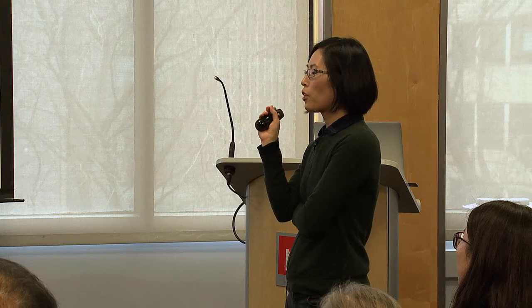Various factors, we ruled out. We think there are 2 factors that contribute to the upturn in crystallization temperature. One is the probability of nucleation, meaning if you think that the nuclei density is fixed, but you reduce the size of the rods, then the absolute number of nuclei that you will have decreases for a small rod. So for a very small rod, maybe you don't have any nucleus. Then you have to first nucleate, and that takes a lot of energy. So how do we verify that?